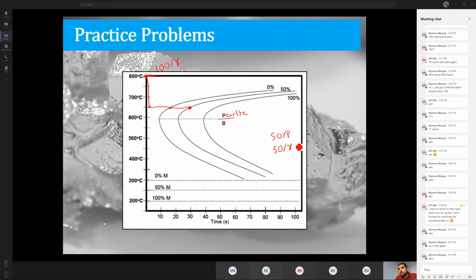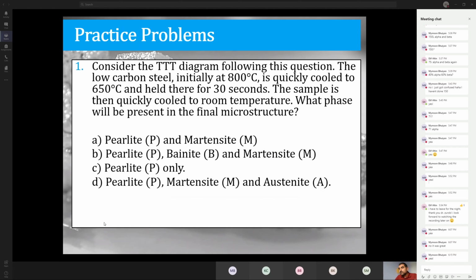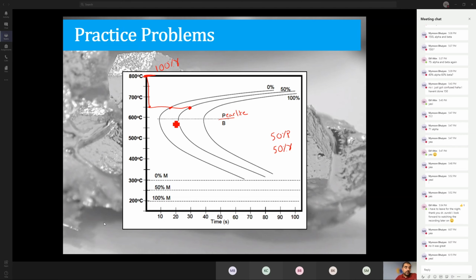Now that's not the final answer, because the question says you hold for 30 seconds and then there is a new step. It says then quickly cool to room temperature. And an important thing to remember about these diagrams, every time the question says then, every time there is a subsequent step, go back to 0 time. So I'm now back at 0 because it said then. And then it said then cool down to room temperature. So I'll just go down to room temperature quickly. So notice in that path, I did not touch pearlite again. I did not touch bainite again. The only lines I crossed are the start of martensite formation. I crossed 50% martensite, and I crossed 100% martensite. So during the quenching step, I made martensite.